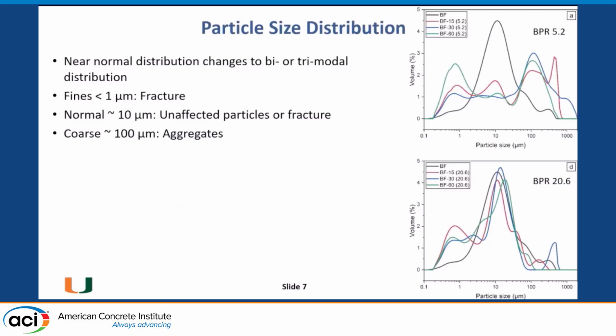So, particle size distribution. The initial particle size distribution is very simple. It's near normal. The peak is about 10 microns. Then after mechanochemical activation, this is almost like parting the Red Sea sort of behavior, where you get a very complicated particle size distribution, which is bi or trimodal in nature.